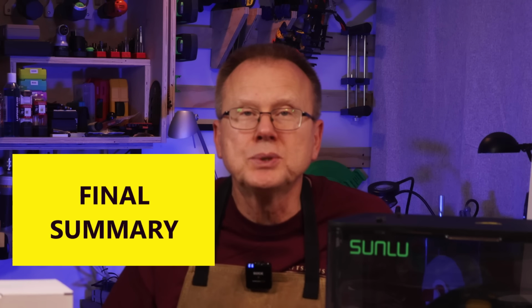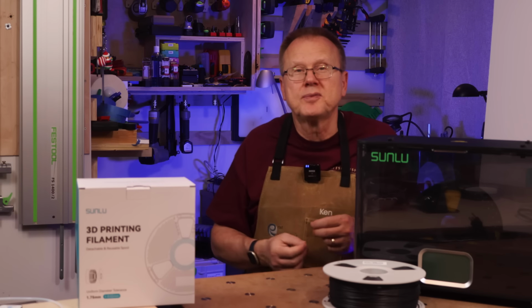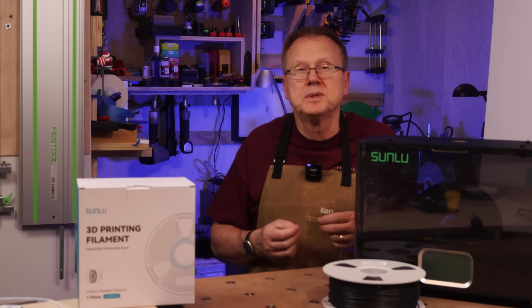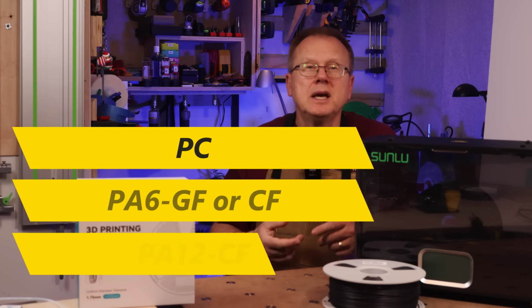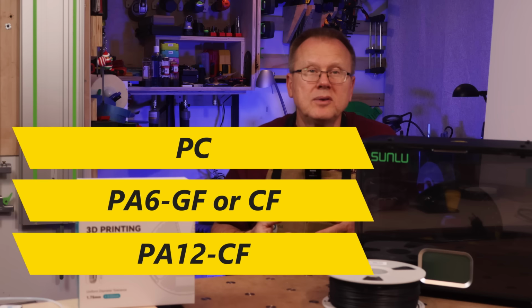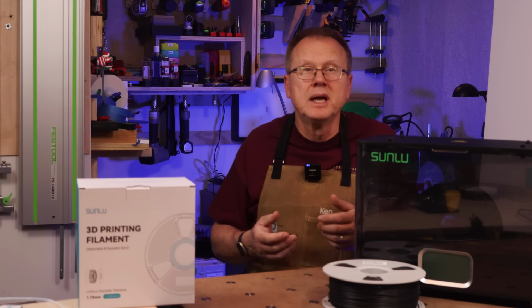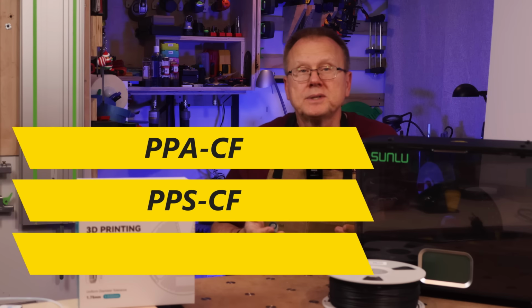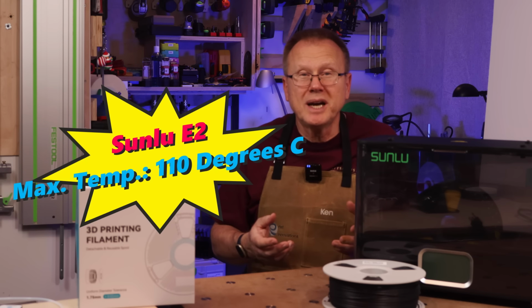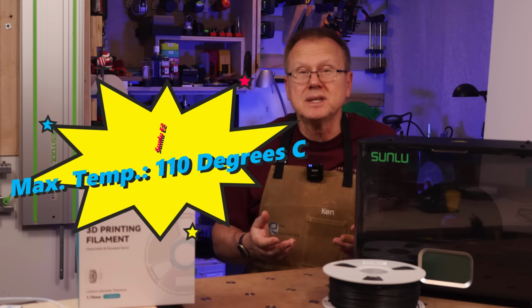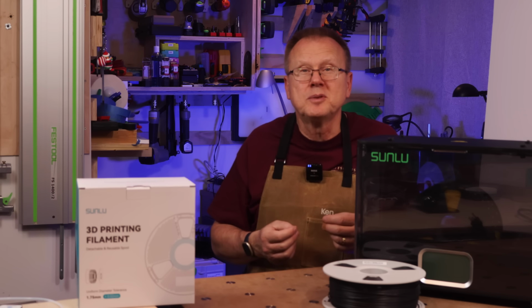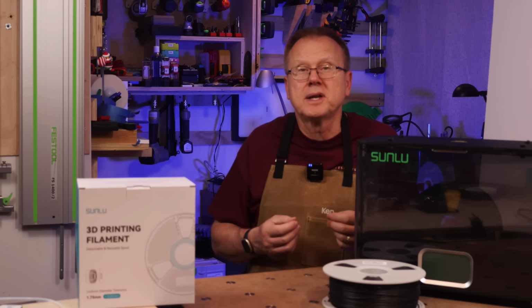The SUNLU Filament Dryer E2 is a very effective filament dryer for all typical materials that you might use for your 3D printing needs, especially for the higher temperature moisture sensitive materials such as PC, PA6, PA12, carbon filled and glass filled, and even PPA and PPS carbon filled. At a maximum drying temperature of 110 degrees C, it's the highest temperature filament dryer that I'm aware of on the market at this time.